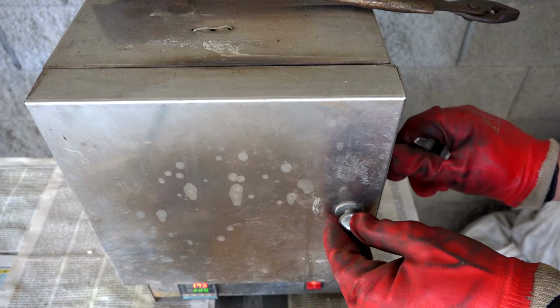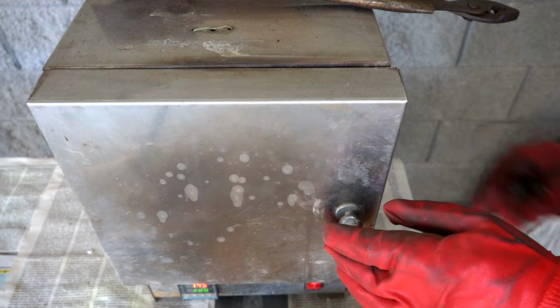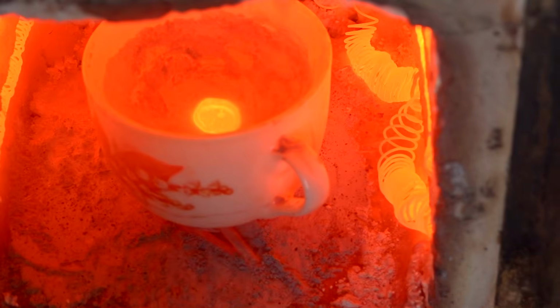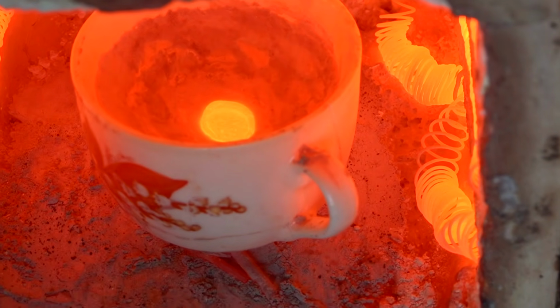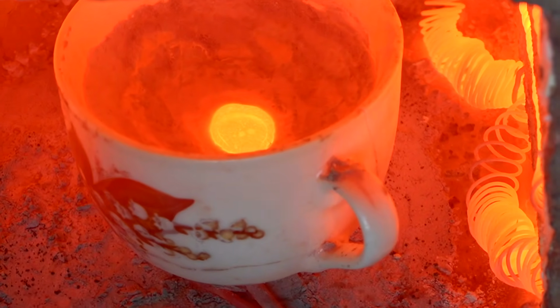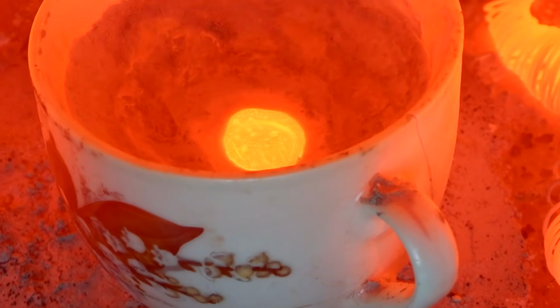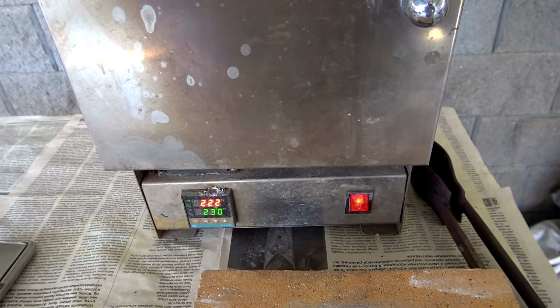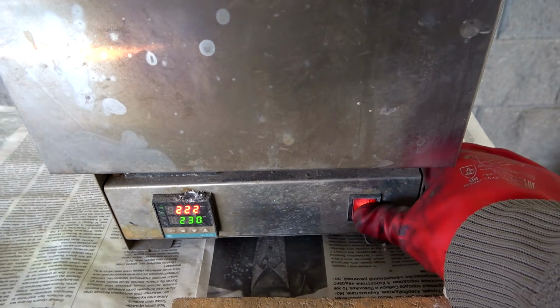The process has begun, and I will be watching it every 20 minutes to show you the last stage of the cupellation. And after 1 hour, the cupellation is approaching the finish line. Note how lead stains flow on the surface of the alloy. These are signs of the presence of precious metals, and the lead evaporates.